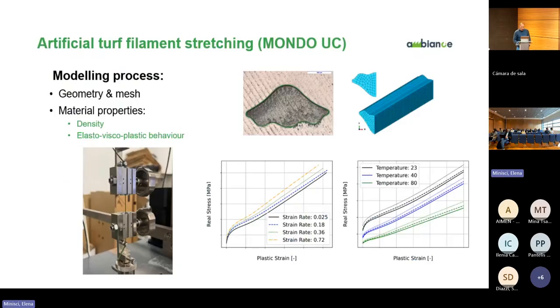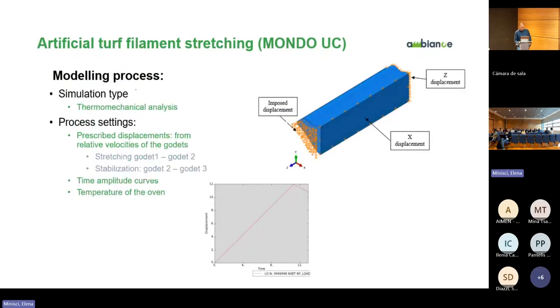The range of temperatures and the range of strain rates are selected to cover the expected ranges in the real processes. This process has been repeated in the AMBIANCE project for several materials and several combinations of bio-based materials. So we completed this characterization in order to model the behavior. Then we need to put boundary conditions on the models, and the work here is to simplify reality into conditions that we can impose directly on the models. In this case, the conditions are just the stretching velocities and the stretching quantity that is controlled by the godet velocities. So we transform this into displacements and velocities for the model, and also the temperatures in the process.